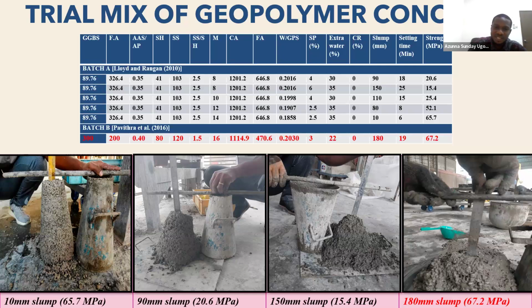So my emphasis here is, it's not the parameters that are wrong, but the method of mix design that I used is what made the output this bad. Now, if I take these same parameters I used for batch A for the density method and input them in batch B, the part that constituted the volume of the concrete and enables me to use the specific gravity of the elements to multiply them, I will still get a very good strength, a strength that is way better than that.